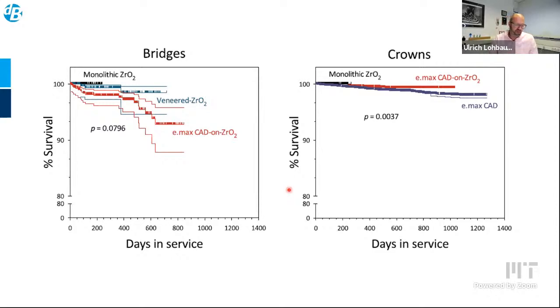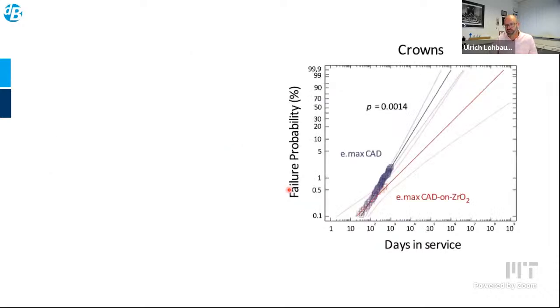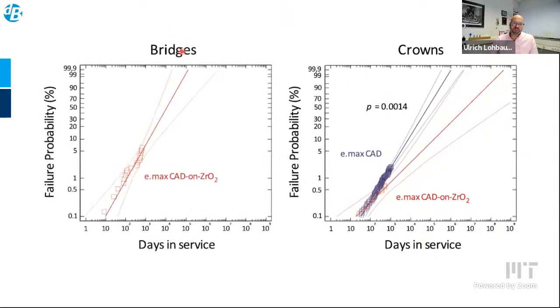So this is a finding that we established on the basis of CAD/CAM manufacturers, standardized manufacturing procedures, and we further analyzed in order to see the lifetime. So we can now do some type of lifetime calculation for those materials, for the crowns and for the bridges. So these are the failed clinical restorations. And then we can say, okay, we have a certain lifetime expectancy of a material, and this lifetime expectancy might be different when comparing the materials, and we can go even further in order to correlate those data with pure crack growth studies on those materials, with degradation and fatigue studies on that material.